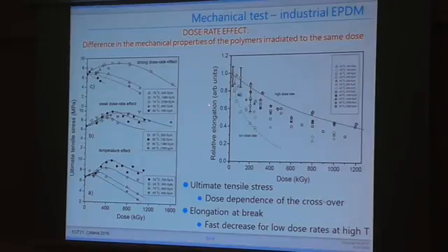Now, with respect to the elongation at break data, this dose rate effect is a bit less obvious because both cross-linking and chain scission induce a decrease of elongation at break. But still, for some extreme conditions like very low dose rate, especially at high temperatures, we can observe that the decrease of elongation at break is much faster than for the high dose rate. So this is a clear indication of dose rate effect.